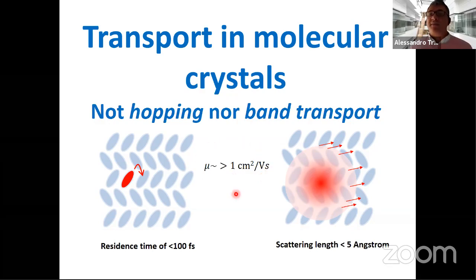And then when you take this number into account and go to the library, you immediately realize that this number is not consistent with a mechanism of transport where the charge hops from molecule to molecule, because it's just too fast. It would imply that the charge will move more quickly than the vibration. That's not really possible. But it's also not possible to use a band type of transport or Boltzmann theory, for example, because it would imply that the distance between two scattering events is actually shorter than the distance between molecules. So this small mobility is not even consistent with localized transport because the scattering is just too frequent, or if you prefer, it's beyond the Ioffe-Regel criterion for scattering.